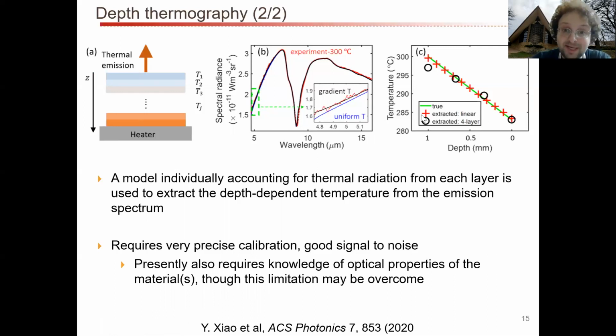And so what you're seeing over here in the experiment, the reason why the spectral radiance is a little bit higher here than it is in our model, is because the region over here, closer to the heater, is hotter than the region on the surface, because the heat is coming from the bottom. And you're seeing some thermal emission from this region making it out, and therefore the spectrum is just a little bit larger over here than it would be otherwise.